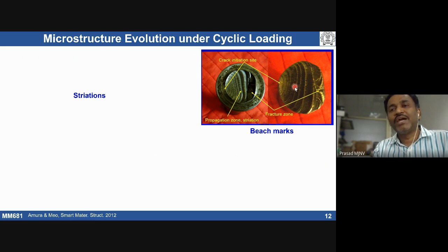So by looking at fractography, even with the naked eye, we are able to see beach marks. We are able to see a beach mark kind of shape. So this basically indicates that the material has undergone cyclic or fatigue failure. This is how people do investigation, on how a particular component failed, whether it failed due to fatigue loading conditions or monotonic loading conditions or something else, or shearing activity. People do this by looking at the fractography. With the naked eye, one can see these beach marks.